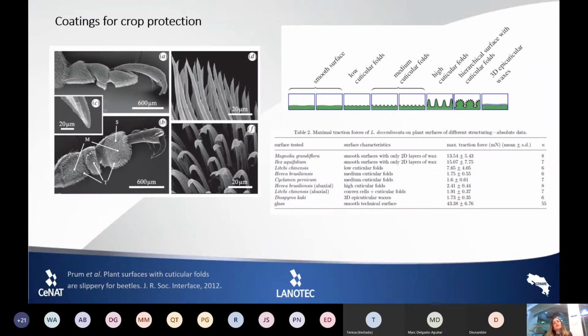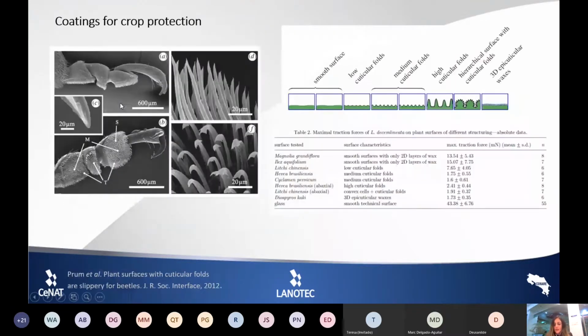Another application that we are working on is crop protection. The biogenic silica itself has these rosettes that we see here. They have a special morphology that has been known in many plants to have this patterned surface that helps to create a roughness that makes the insects not adhere to the surface of the plant. So this biogenic silica can not just be used as a biofertilizer, but also can be used for producing a natural coating for the plant, for avoiding the insects being on the surface and damaging the plants.